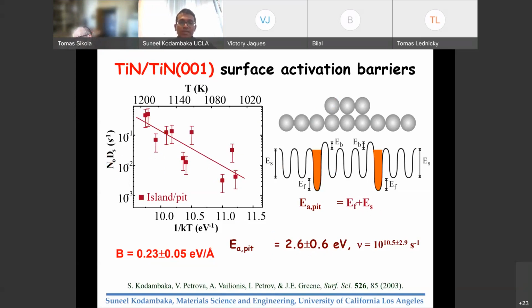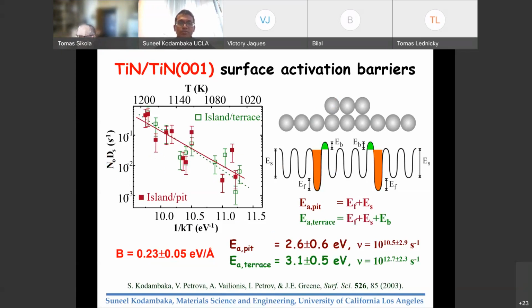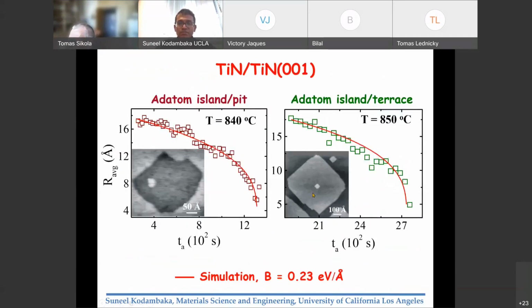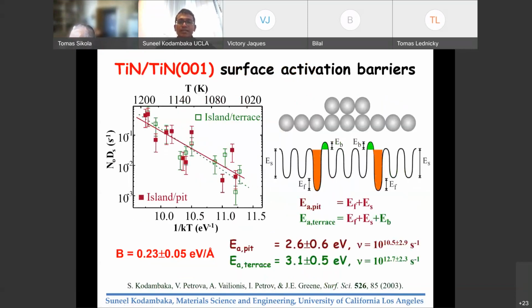And this is for the atom islands within the vacancy islands. The same type of experiments are done for atom islands on top of terraces. For these, there's an extra barrier, the Ehrlich-Schwoebel barrier, for the atoms to jump down the step. For that, we get a total activation energy of about 3.1 eV, but within the errors of measurement, these are about the same, meaning that the Ehrlich-Schwoebel barrier for atoms to hop down titanium nitride steps is within the errors of our measurement. So from the island decay measurements, from the changes in the sizes of islands as a function of annealing time, we can extract some of the parameters such as the activation barrier for surface diffusion and also the Ehrlich-Schwoebel barrier.